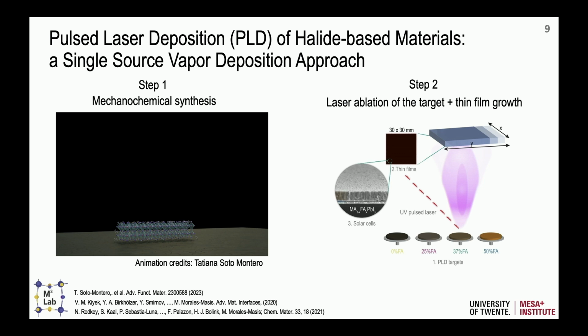So because we can do this step, we can actually make targets with different compositions and then tune the composition of our films. And that's basically how it works. We have a laser ablating the target. This is our substrate. And because we want to cover a little bit larger areas, we have the substrate that is actually scanning in the XY direction.